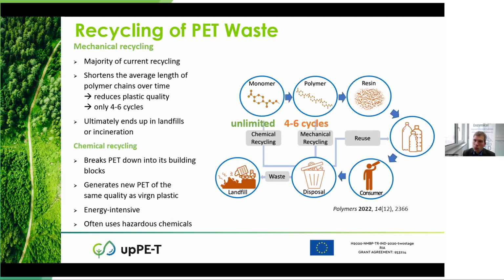There are currently two main routes to recycle plastics. The major route is still mechanical recycling, which means that the plastic is shredded into small pieces, melted, and reformed into new containers. However, this shortens the average length of the polymer chains and thus makes the plastic weaker, more brittle, and less useful. Consequently, the PET can usually only be recycled mechanically around 4 to 6 times. And so ultimately, even if it is recycled 4 to 6 times, it also ends up in landfills or incineration, where the material in the end is lost.